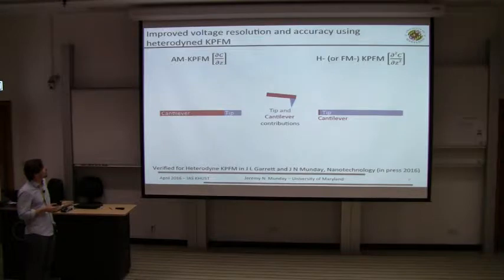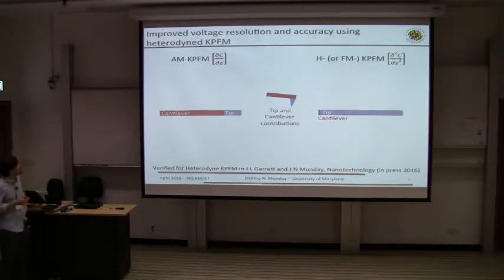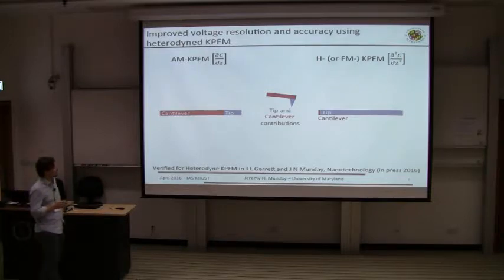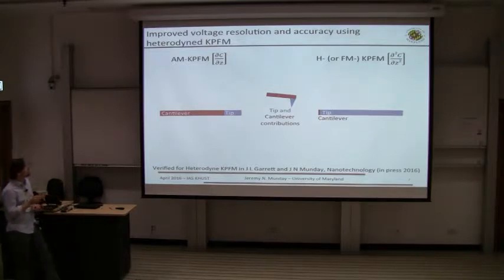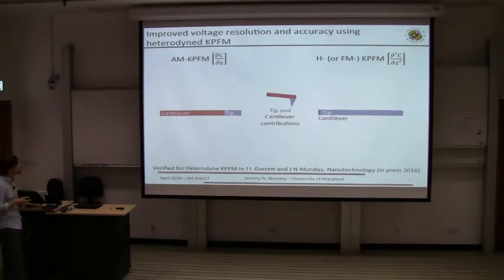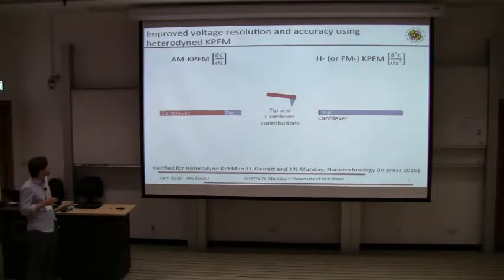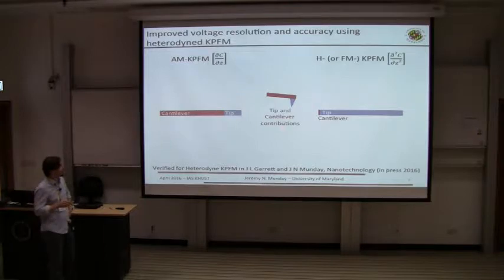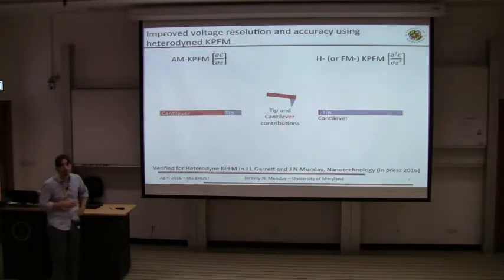And so I'm going to talk about two kind of common ones here. One is an amplitude modulated version of Kelvin probe force microscopy, and the other one is a frequency modulated, or in the case of some of the stuff that we're doing, it's a heterodyne method, but I'll just lump them together, basically as things that go as the derivative of the capacitance, and things that go as the derivative squared of the capacitance. And so with these different techniques, with both of them, you're getting contributions from both the tip of your cantilever and of the actual cantilever itself, because there's some sort of distance dependence, it's electrostatics, you've got interactions with both of these things.